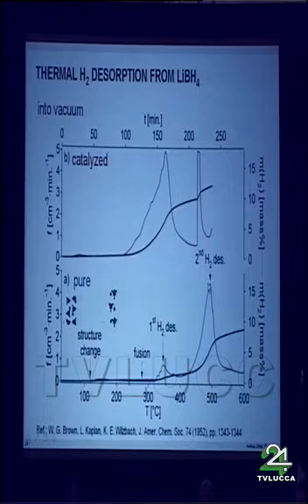Now, okay, I'm almost over with my time. I will just show you one example of lithium boron hydride, because that's the complex hydride with the highest mass percentage of hydrogen. And here on the bottom in the blue line you have the decomposition of lithium boron hydride of the pure sample, and the red one is a catalyzed sample. And you can see also with a catalyst in lithium boron hydride we can reduce significantly the desorption temperature. However, this is desorption into vacuum, and this measurement doesn't tell us directly the decomposition temperature. It's a mixed information of kinetics and stability.